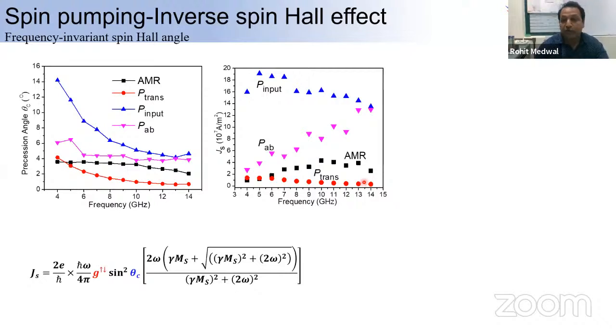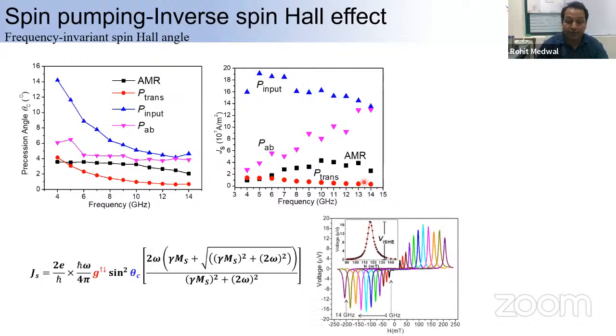So what we did, we also tried to measure the inverse spin Hall voltage from another set of devices with a different device configuration. And what we clearly observed for the inverse spin Hall effect, this is the final result, because this is the final output we have to correlate, and this is the intermediate result. At initial frequencies it just increases, and after that it starts decreasing, which clearly matches our AMR results. In the AMR results also, the spin current first increases and then decreases.